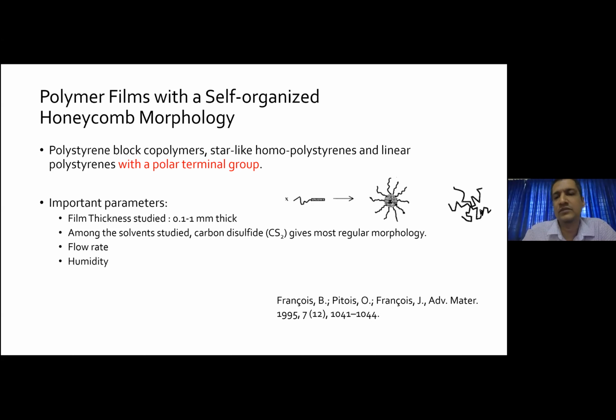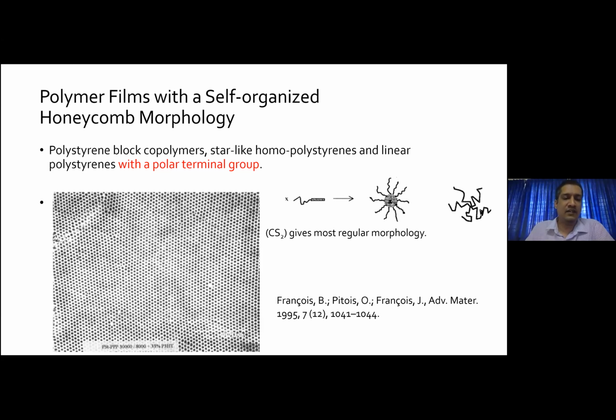So with this, they wanted to know whether it is so essential to have this kind of aggregate. So they tried with simple polystyrene and the star branched polystyrene, and found that these kinds of patterns are well obtained in the case of the block polymer and star polymer, not in the case of simple polystyrene, using their experimental conditions. And to add one more functionality to the breath figure patterns, they tried to mix or blend with poly 3-hexyl thiophene. Poly 3-hexyl thiophene is also a hydrophobic molecule, and the one they have taken is of low molecular weight compared to the polystyrene block polyparaphenylene.